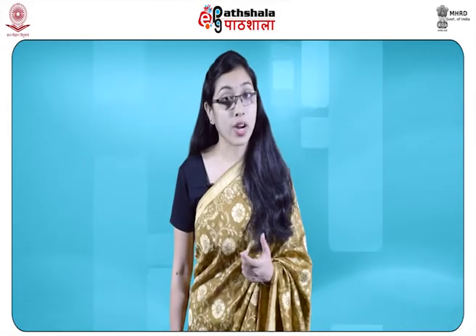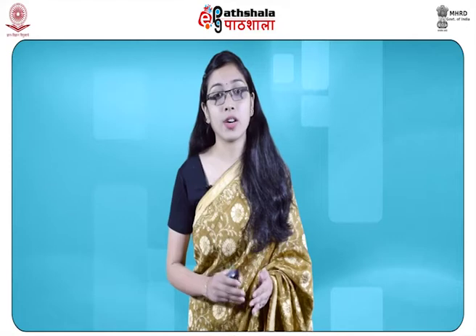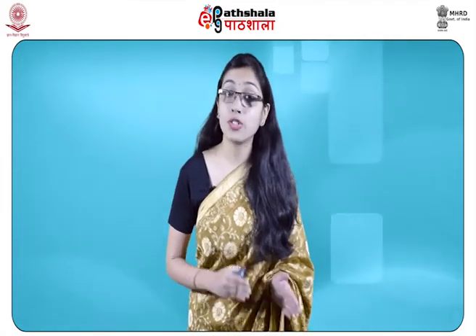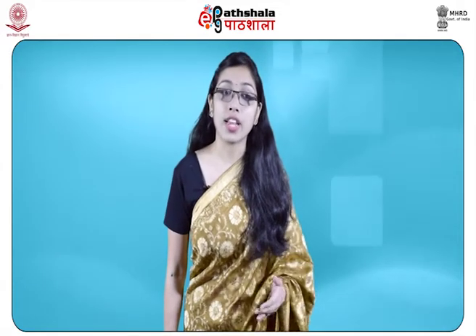With a dendrimer concentration greater than 10 to the minus 4 molar, the solution was quite tacky and produced too much background via the indiscriminate adherence to the sample rather than the preferential adherence to the fingerprint on the sample. Thus, the dendrimer concentration employed ranged from 2 to 8 times 10 to the power minus 5 molar in methanol, as well as in the 1:9 methanol to water preparation. Fingerprint staining with the methanol and methanol to water formulation simply involved dipping the aluminium foil and polyethylene samples and then letting them dry completely.